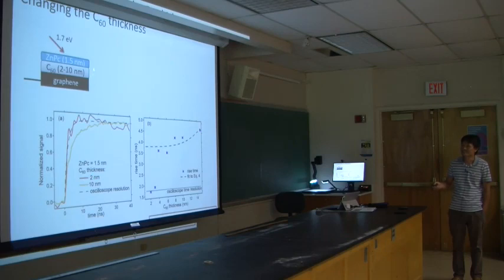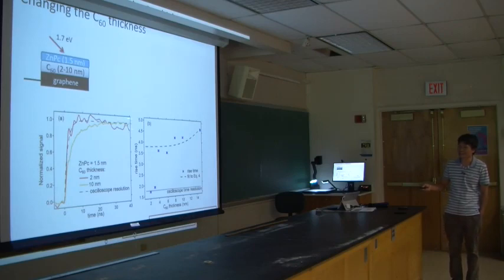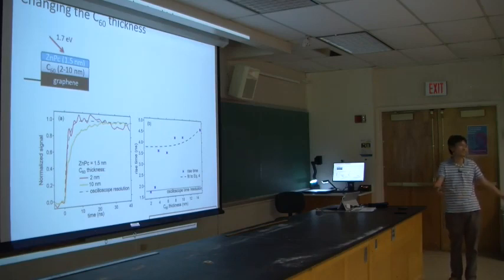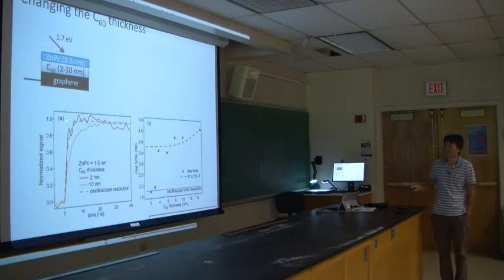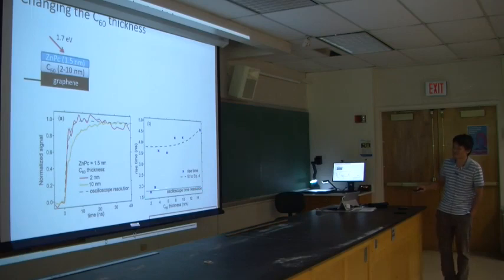We change the C60 layer thickness again, and obtain the rise time of the signal, which is how fast we detect the free carriers. Of course, for thicker layers we expect that to be later, since excitons need to be separated and then electrons need to transport to graphene. We measure that as a function of thickness. For very thin films, we don't have the time resolution to probe those. It's below the time resolution of our oscilloscope, so it's limited by the oscilloscope.